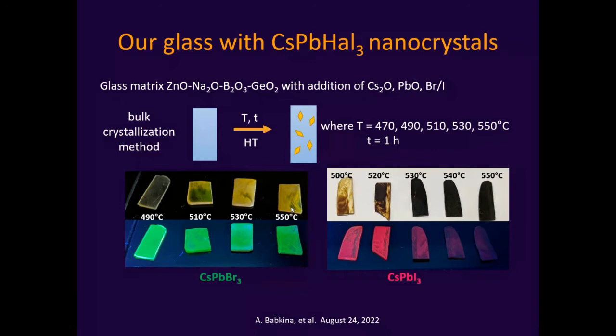So as you see, our first attempts are good, but not good enough, because the glasses are not very uniform. But still, we took a borogermanate glass matrix, used the bulk crystallization method, and obtained nanocrystals inside of the glass matrix at different temperatures of heat treatment, using different durations of heat treatment. And you can see we have these nanocrystals and these nanocrystals, so bromide and iodide nanocrystals of cesium lead perovskite.